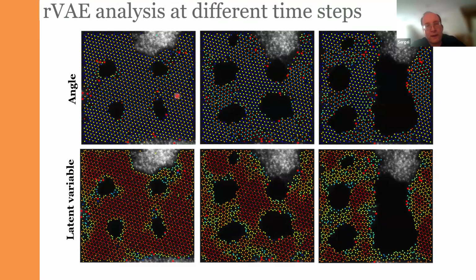So this is how the VAE is going to look at this data set. So we get the angles image. The angle just shows the two different possible orientations of sp2 bonded carbon. These are the latent variables. So notice that once you look at this image, the meaning of the latent variable becomes immediately obvious, because if the carbon is ideal, so it's an ideal hexagonal lattice, the latent variable is close to 1. If we have disorder, then the latent variable is very different from 1. So it's a way how we can identify them.